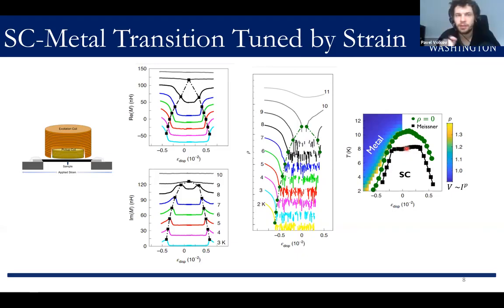But the resistive transition is measured in zero field, so the vortices shouldn't matter there. Yeah, sorry, I misspoke. I just meant the critical currents depend on the domains and the density of the domains. Okay, thank you. For most superconductors, the Meissner transition is always, in experiments, slightly lower than the resistive transition. You just need a zero resistance path in order to have zero resistance. Right, but here it's more pronounced when you have a twinned sample. That's right. So to quantify this will be an interesting problem.